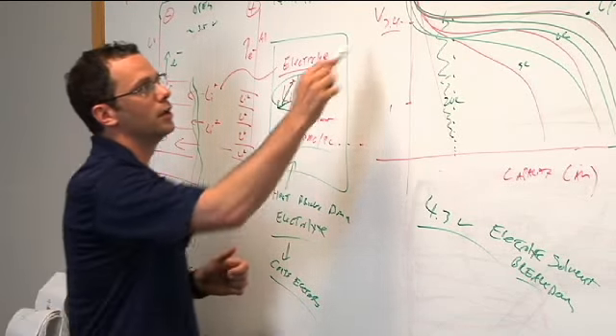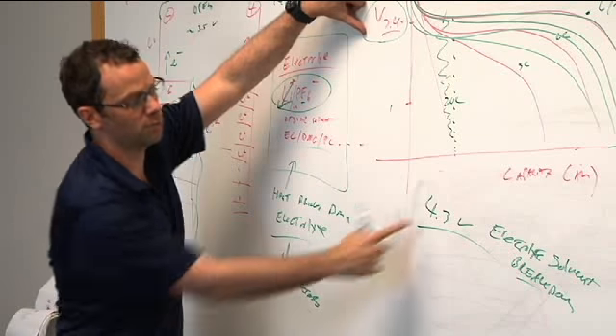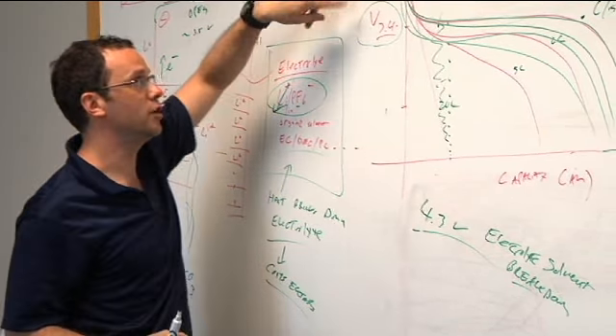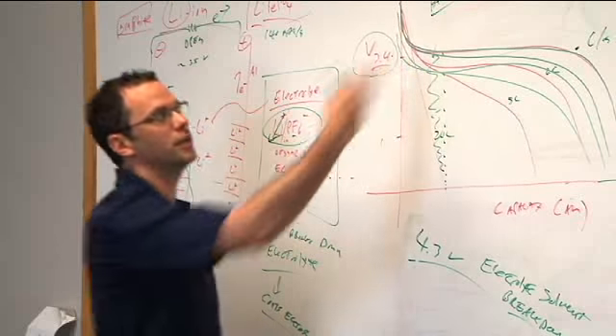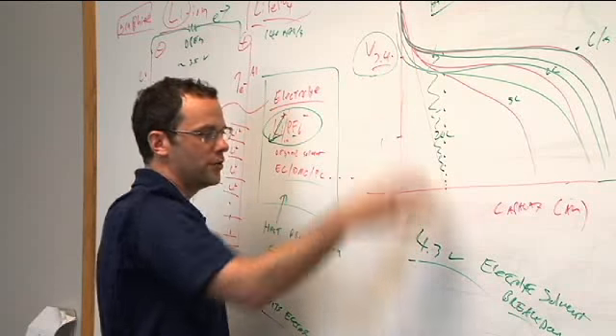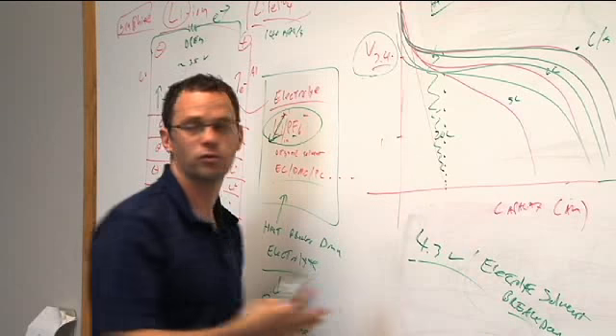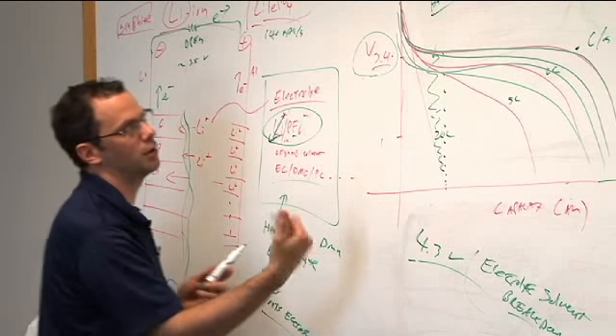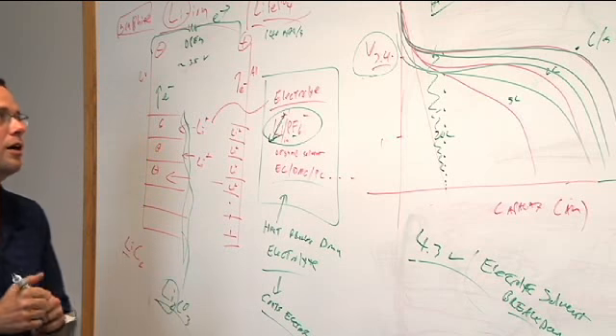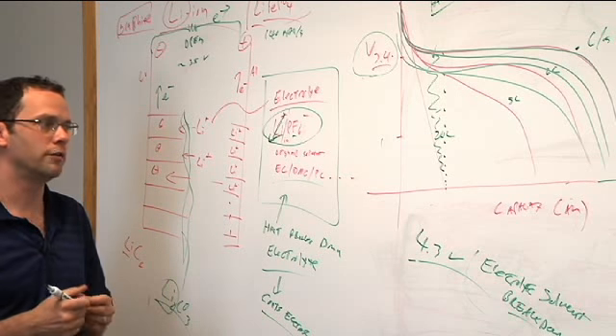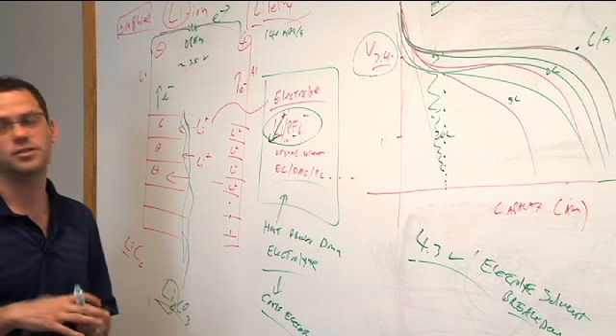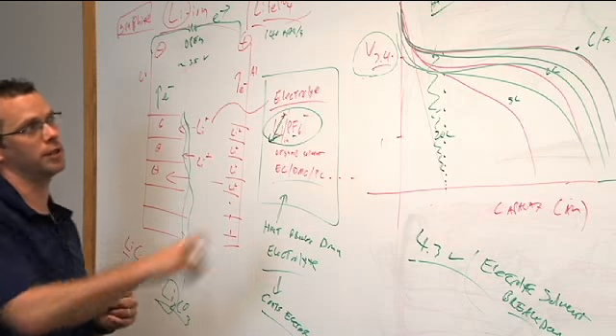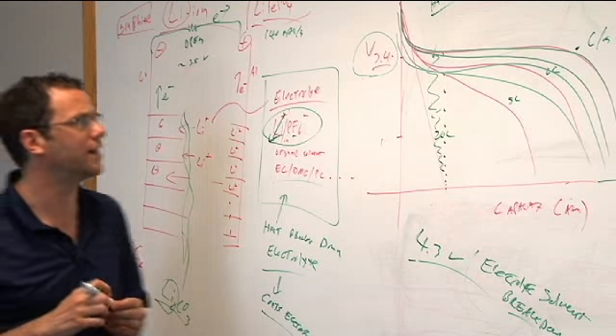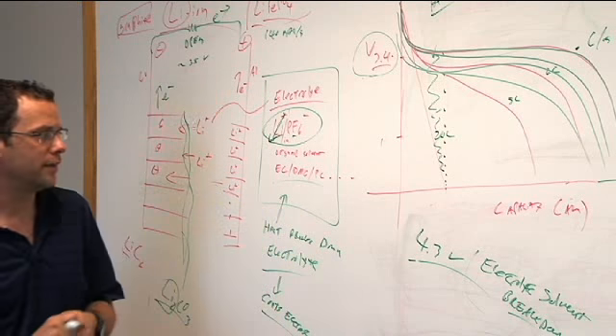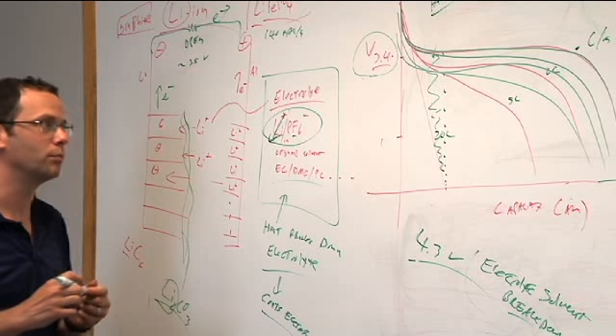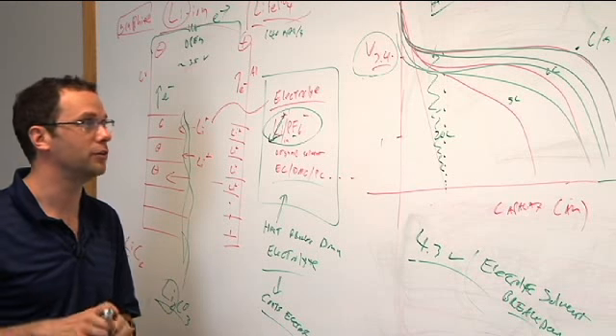But because you are charging to a lower voltage, you have much more wiggle room before you get to this danger point. That's good. And indeed, because you're at this low voltage, you're going to be much less apt to be splitting the electrolyte at the cathode as well. So it's more safe. I would just say standard 4 volts, and you're going to be okay. Also, stay under 140 degrees C. That's kind of a magic number for this particular chemistry. If you dwell at high temperatures for a long time, eventually they will fail and they will blow up, maybe. It depends on who's making your cells and what the deal is.